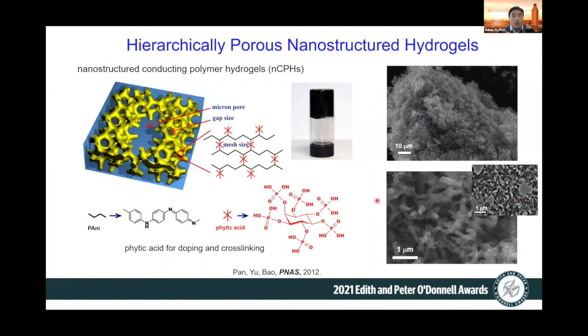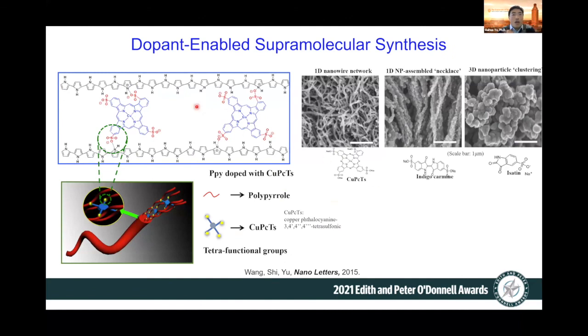And then we can tune their surface area from tens to hundreds of square meters per gram. And their electronic conductivity, based on this conducting polymer, can also range from a few to 1,000 Siemens per meter. So the next example is by rational selection of different dopants, so we can explore this supramolecular self-assembly mechanism.